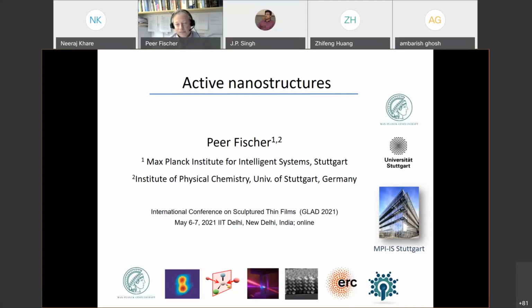And is there anything special about this titanium dioxide? Like what phase would it have to be? Yeah, between anatase and rutile, there are some more effective ones. After annealing, you end up with anatase, and it tends to be more effective in the catalytic process. But if people want to work with this, you can even buy particles that are synthesized. So you can buy titanium dioxide particles, and after deposition and just a very simple annealing process, we can ensure that they all are fairly active. So it's not a difficult step. Okay, great. Thank you.